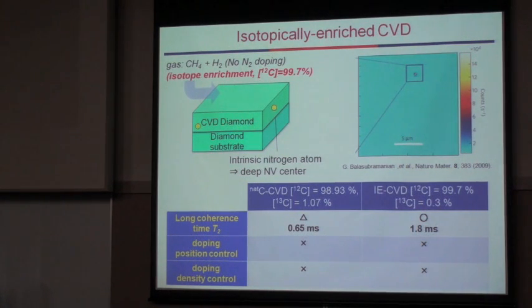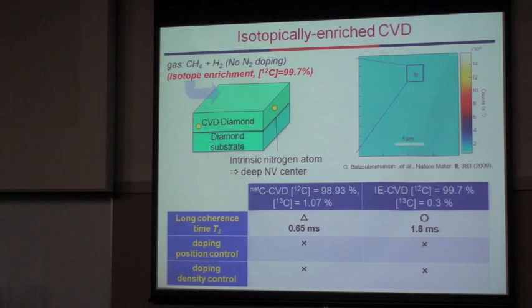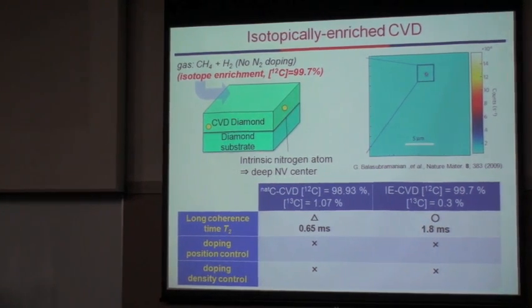The CVD method is another technique to dope the NV center in diamond. Especially isotopically enriched CVD is an effective method to obtain the NV center with longer coherence time. Other groups reported millisecond-order coherence time in isotopically enriched CVD diamond.